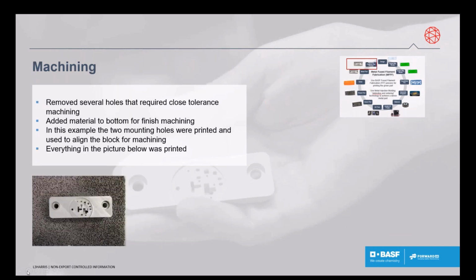Machining. The block in the picture below, that's the one we've been seeing through this presentation. It holds the electronic contacts for assembly. So these contacts lay over each other and they drop into those various shaped holes you see in the block. We removed some very close tolerance holes that we machined in later. We did add material to the bottom and we machined it flat with the top. The holes on the outside are used to align the block for machining. The parts were printed Z up, sintered Z up, and machined from the top Z up.